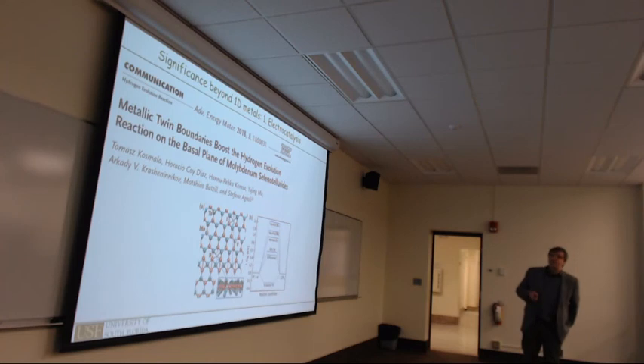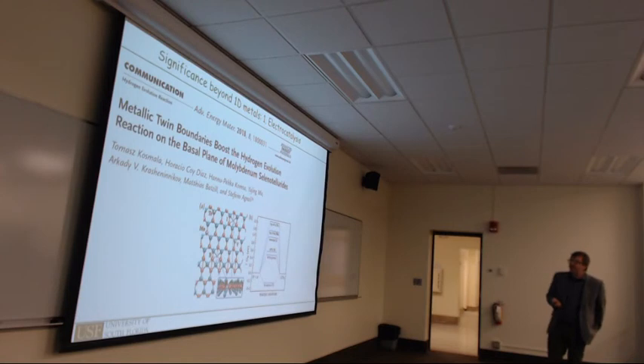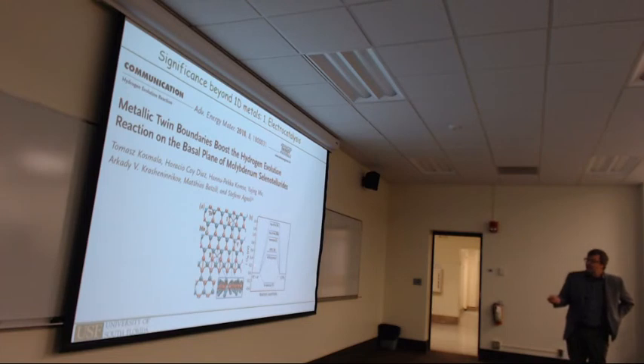All right. Now, why is that interesting? We asked Stefano in Padova to do some electrocatalysis on it, so to look at hydrogen evolution reactions, and Arkady then did some DFT calculations. And essentially what we saw is an enhancement of the hydrogen evolution, which makes sense with the DFT calculation for the barrier of the hydrogen evolution.